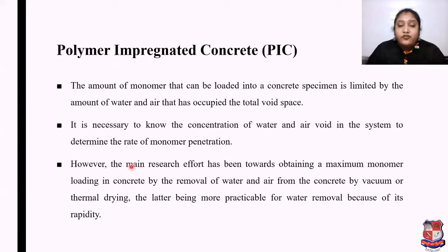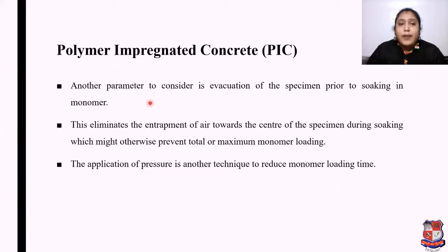However, the main research effort has been towards obtaining maximum monomer loading in concrete by the removal of water and air from the concrete by vacuum or by thermal drying, the latter being more practicable for water removal because of its rapidity. Another parameter to consider is evacuation of the specimen prior to soaking in monomer. This eliminates the entrapment of air towards the center of the specimen during soaking, which might otherwise prevent total or maximum monomer loading. The application of pressure is another technique to reduce monomer loading time.